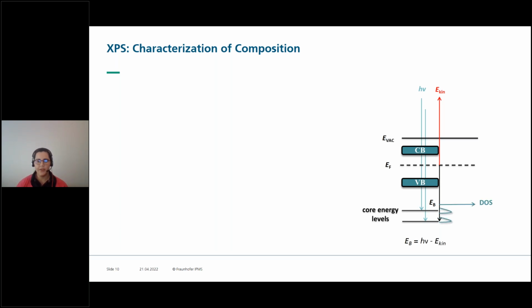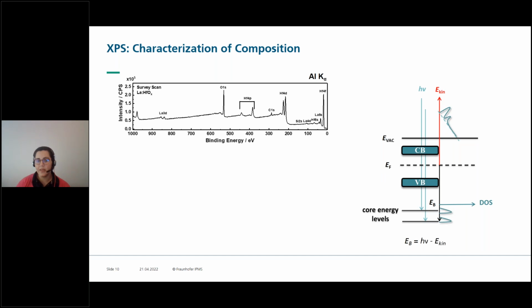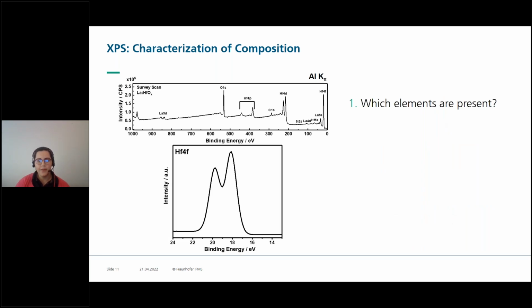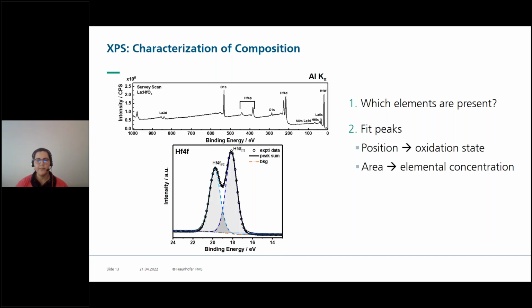Now, the core energy levels have a characteristic density of states. And as the photoelectrons are ejected, the spectrum is recorded mirroring these density of states. So up here you have a survey spectrum, which gives an overview of all the elements in your material. This is, for example, a survey scan of a doped hafnium oxide material. Here we have a high resolution scan of hafnium core orbital level 4F. So we can tell, like I said, from the survey spectrum which elements are present. When we fit our peaks, we can get the position, which gives us an idea of the oxidation state. When we fit the areas under the peaks, we have an idea of our elemental concentration, and therefore we determine our composition.